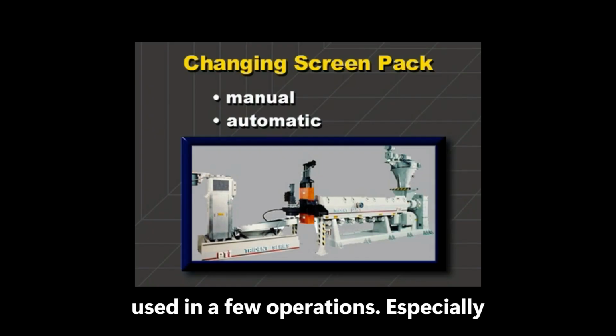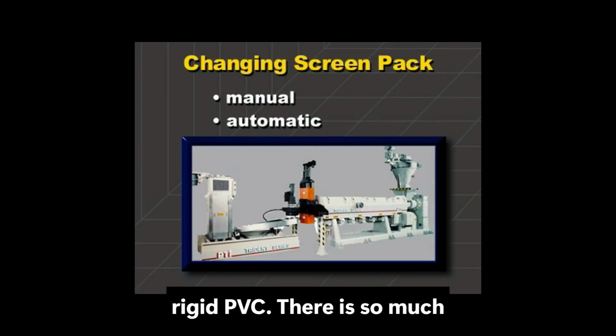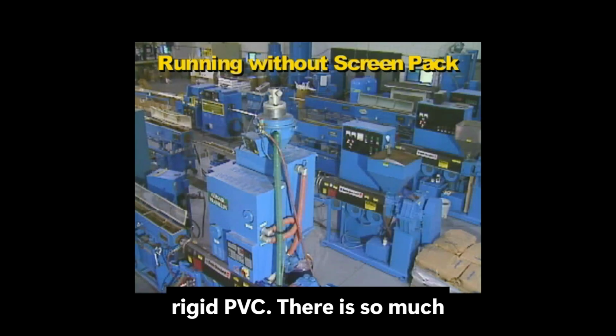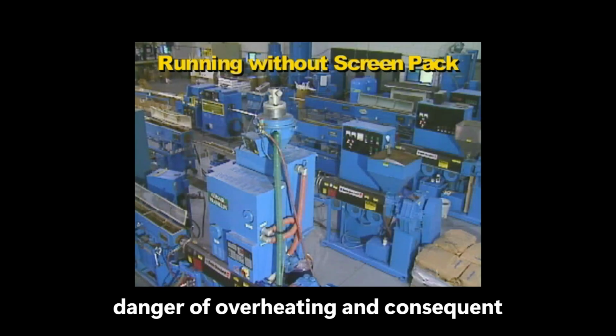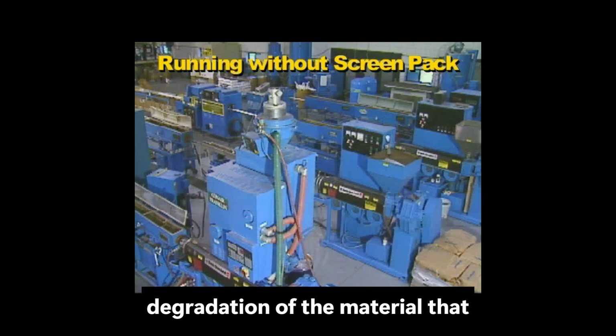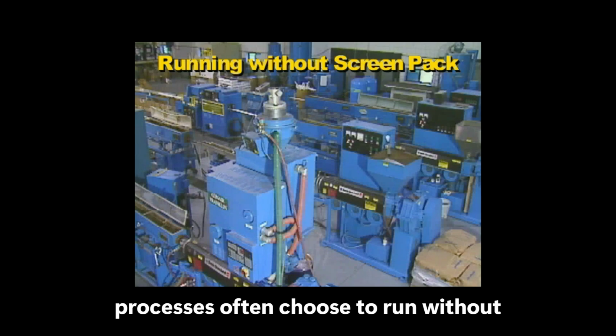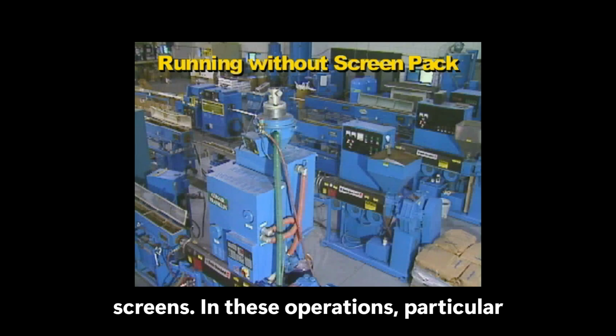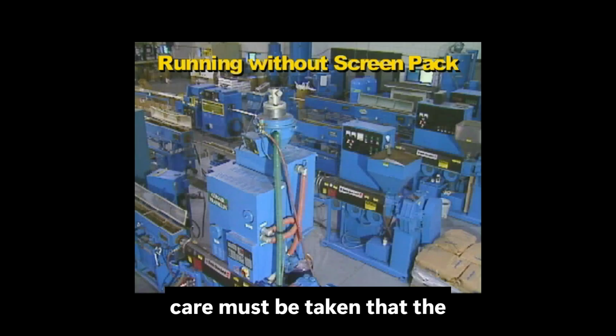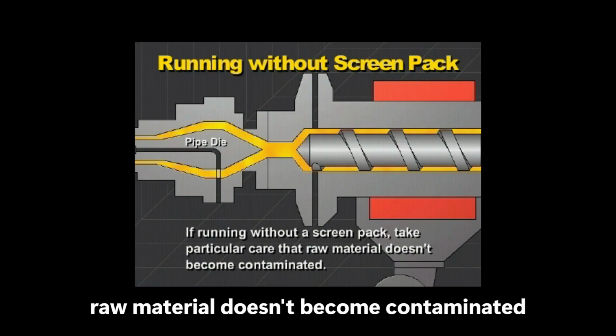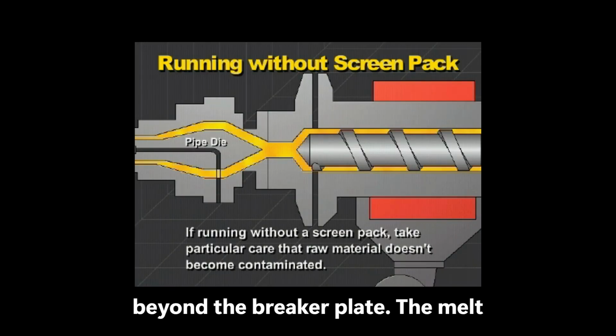In a few operations, especially rigid PVC, there is so much danger of overheating and consequent degradation of the material that processors often choose to run without screens. In these operations, particular care must be taken that the raw material doesn't become contaminated.